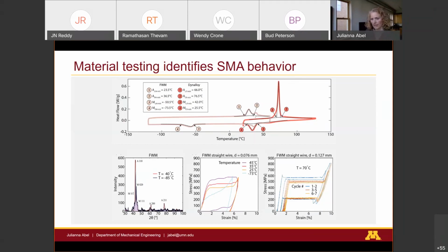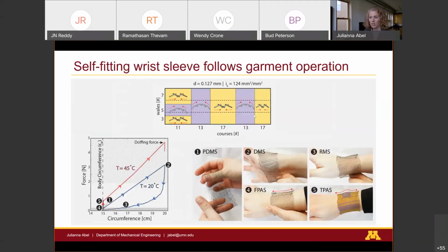And so we're really excited to have access to this material so that we can demonstrate this on body. We only have a small amount, and so we did a wrist garment, a self-fitting wrist sleeve, and used the topography of the wrist to have a custom design pattern. And when we pulled it over, it followed a very similar qualitative performance, where initially it's flexible, you stretch it over your hand to where the wrist is larger, and once it's on the wrist, it relaxes and the body heats it up and it starts to apply some pressure.